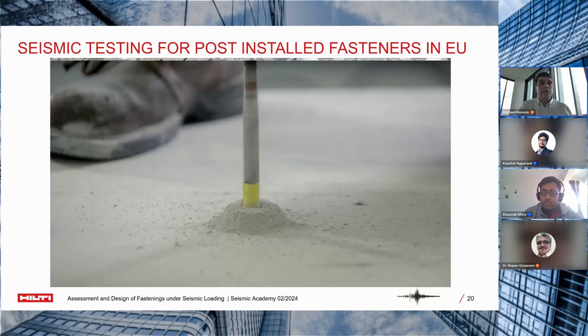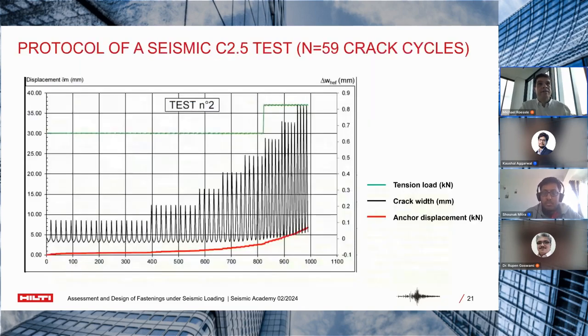And just showing the next slide, a typical test protocol that we are seeing here. That diagram is showing an applied tension load, that's the green line in this diagram. The black curves, that's the crack width. So you see that the crack width is cycling, it's closing and opening up to 0.8 millimeters. So that's really typical crack cycles that we have found in those researches, that this is typical for concrete structure during a seismic event. And then you see the anchor displacement, that's the red line